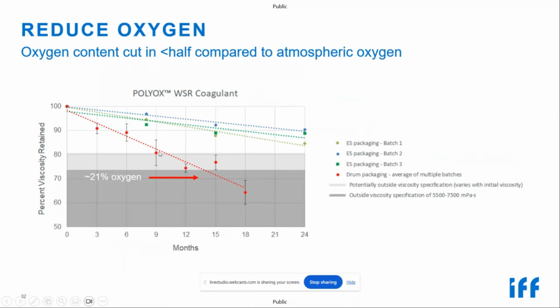So you can see the red lines, this is coag, the coagulant grade. It's in specification up to 6 months. At 9 months, maybe some of the batches were in spec and some were not. This is why we have the 6-month retest interval. For these packages in the blue, green, and light green in the new extended stability packaging, you can see that we are well above the potential min spec, even out to 24 months or 2 years. So reducing oxygen and good storage conditions can be key to extending the usable life of polyethylene oxide.